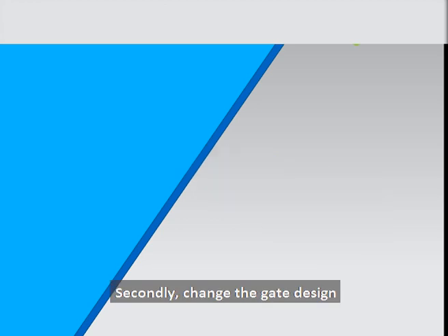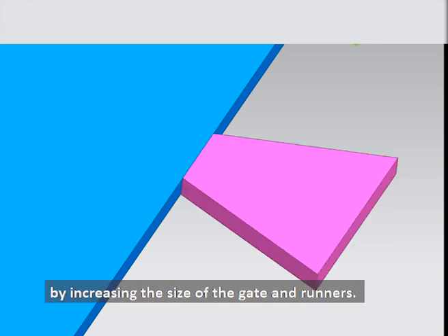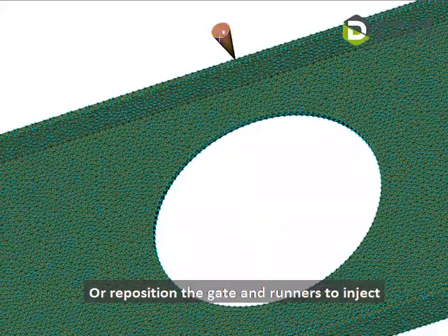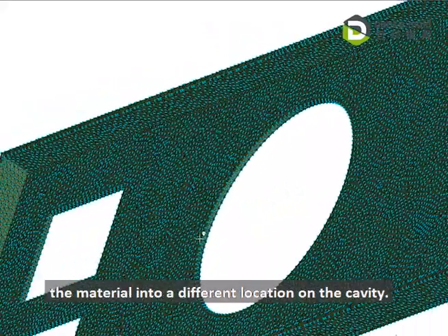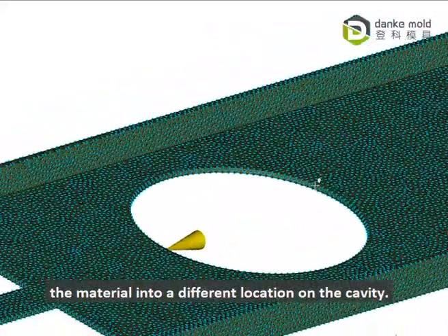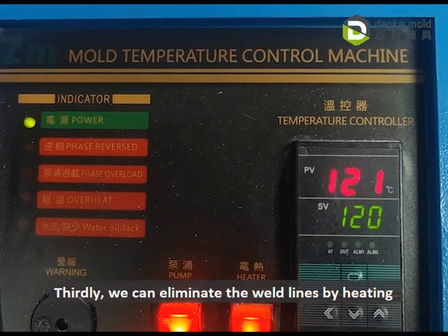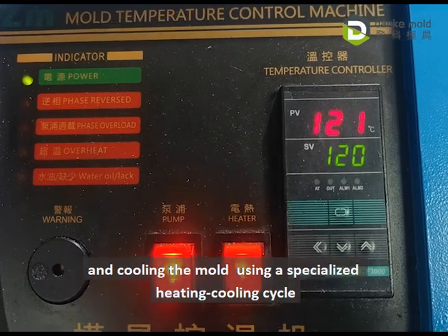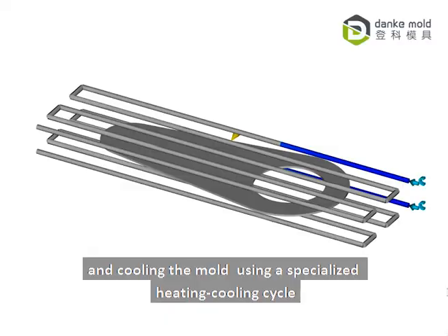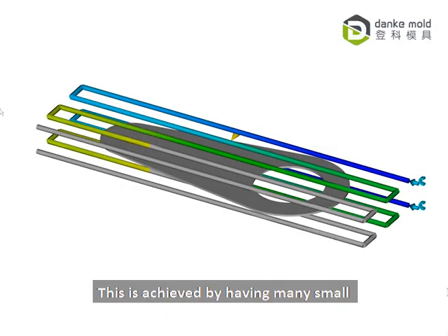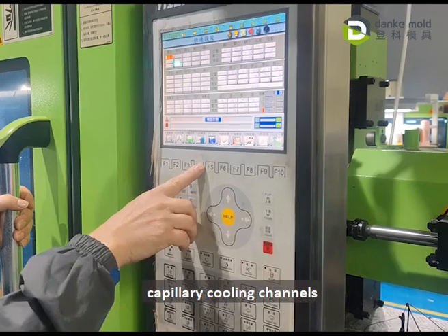Secondly, change the gate design by increasing the size of the gate and runners, or reposition the gate and runners to inject the material into a different location on the cavity. Thirdly, we can eliminate the weld lines by heating and cooling the mold using a specialized heating-cooling cycle. This is achieved by having many small capillary cooling channels.